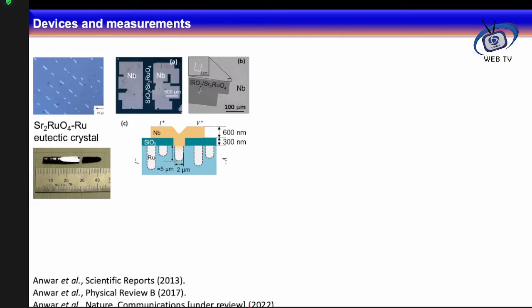But if you grow the metal at the top of this ruthenium metal, which is the inclusion, then you can establish a very good electronic interface, because it is the interface between two metals. And then we develop the devices in this configuration, where I first deposited the silicon oxide just to isolate all of this single crystal, except over one single ruthenium.